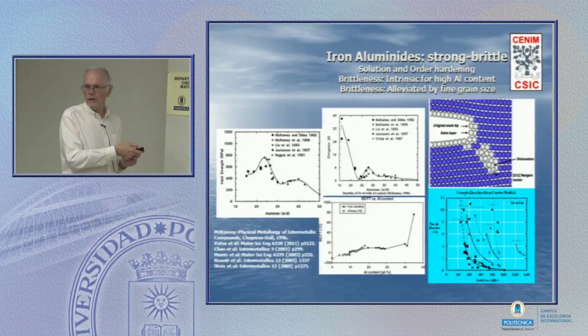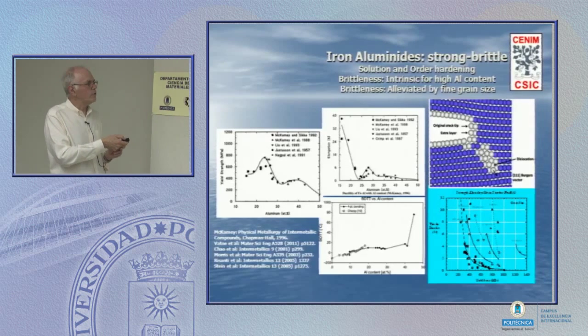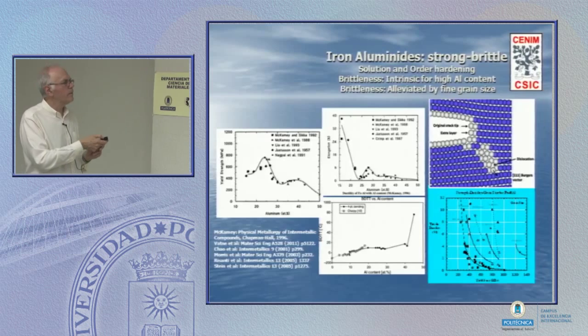Now, unfortunately, if I look at ductility as a function of aluminium content, I've really got the reciprocal. Iron, or iron with a small amount of aluminium, is ductile, tough. When we reach Fe3Al, there's almost no ductility, very poor toughness. But as I come back towards FeAl, the ductility comes back somewhat.